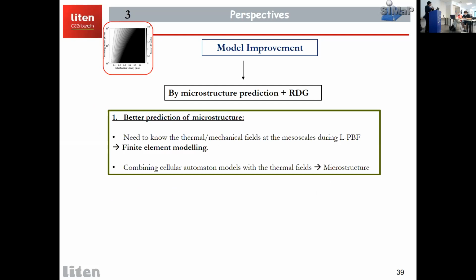To do that, predicting microstructure, we can think of doing several finite element simulations based on the local thermal and mechanical fields at really small mesoscales, taking into account the L-PBF processing parameters. And by combining this with the microstructural models using cellular automaton models, for example, this is how we can probably predict the microstructure in L-PBF for a given composition.